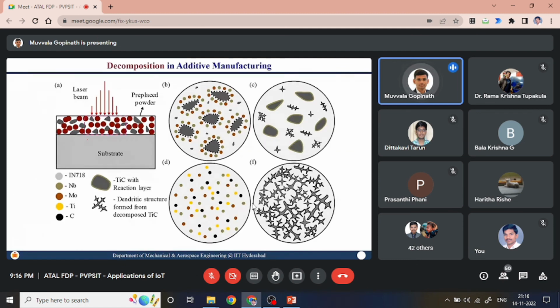Now assume that you are making a composite. Composite means, let us say, Inconel 718 plus some titanium carbide or tungsten carbide. Whenever you are introducing ceramic particles, essentially the ceramic particles should not melt or decompose. They should be embedded into the metal matrix, with some kind of proper tailoring with the matrix, right? Which essentially means whenever you are melting this kind of powder, your Inconel, which is the metal matrix, melts and the ceramic particle doesn't melt.